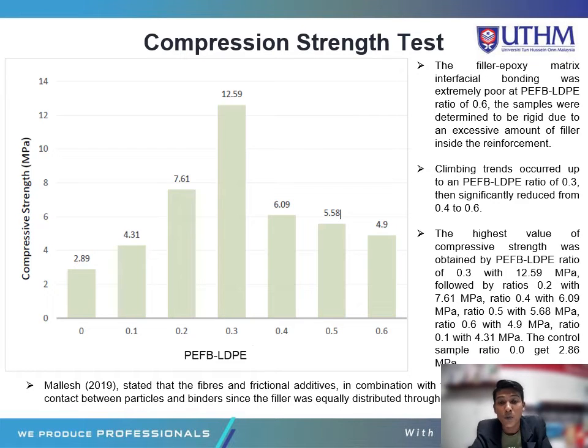The highest value of compressive strength was obtained by PEFB LDPE ratio 0.3 with 12.59 MPa, followed by ratio 0.2 with 7.61 MPa, ratio 0.4 with 6.09 MPa, ratio 0.5 with 5.68 MPa, ratio 0.6 with 4.9 MPa, and ratio 0.1 with 4.31 MPa. The control sample, ratio 0.0, got 2.86 MPa. Mallesh 2019 stated that the fiber and frictional additive in combination with the binder produced good contact between particles and binder since the filler was equally distributed throughout the composites.